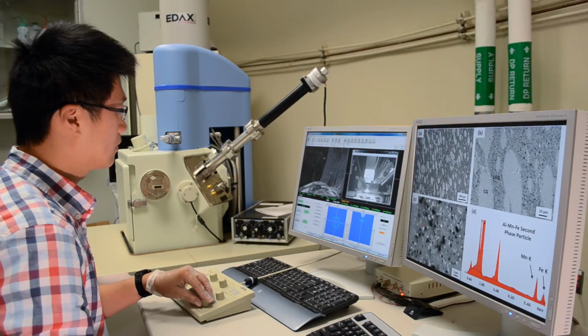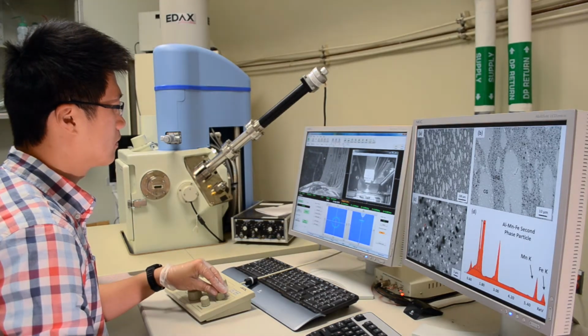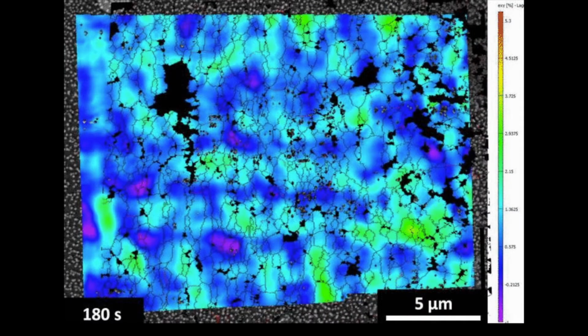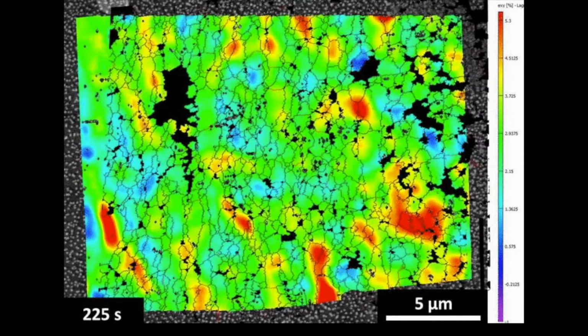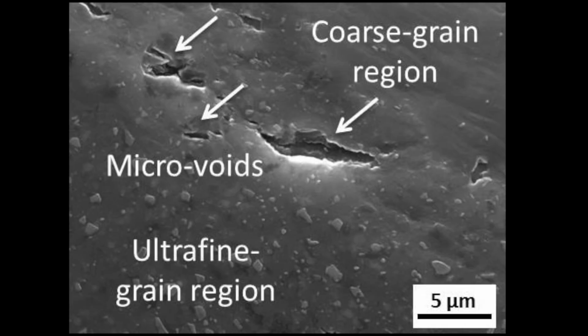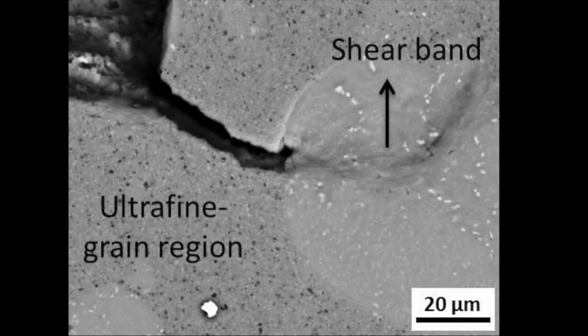We can use digital image correlation software to evaluate these images to track the evolution of microstrain and the formation of microvoids. Using this technique, we can also see how cracks propagate, frequently through this heterogeneous microstructure. The data we have collected indicates a significant improvement in strength and toughness in these aluminum nanocomposites.